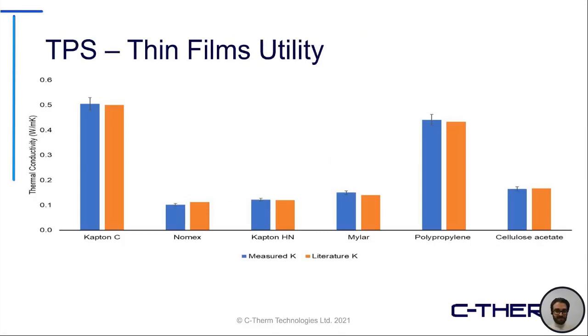So you can see here some examples of data of some different materials that are measured compared to their literature value using the thin films method. And really we see some of the variability max on the upper end of about 10% for some of those samples, but it really gives you the ability to test some materials that are down to a few dozen microns thick. Whereas in other methods, you would require to have that stacked up to multiple layers, or be testing the bulk sample, and wouldn't be able to get that representative measurement of that thin material.